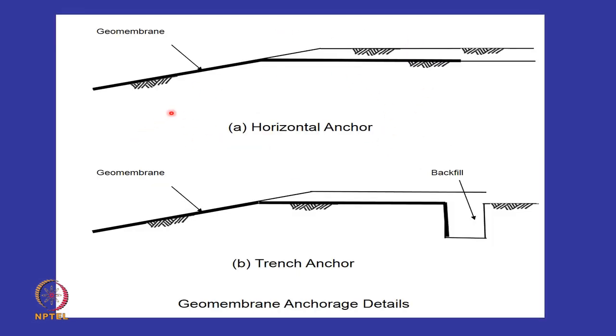And as I told you, the geomembrane has to be anchored at the top, otherwise it has a tendency to slip down. When you put soil on top, that will have a tendency to make it slip down. So either the geomembrane will go into a trench, or if there is sufficient horizontal distance available, it will be run out horizontally. So these are the two ways in which you can hold the geomembrane in position.